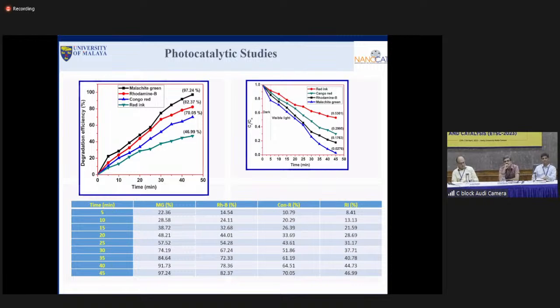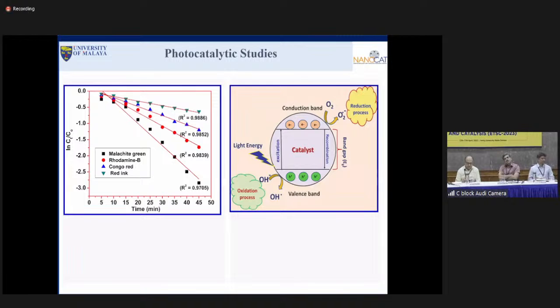From this graph, you can see that malachite green, the black one, shows 97.24%, followed by rhodamine B at 82.37%, then Congo red at 70.05%, and 46.99% for red ink. We have also plotted the graph between the degradation rate constant and time. In the absence of light, there are no changes, but under visible light you observe significant changes in the photocatalytic effect. And then this one is the first order kinetic study.